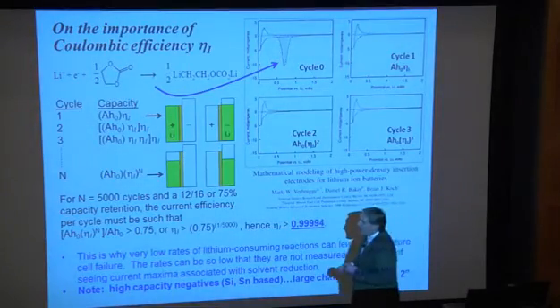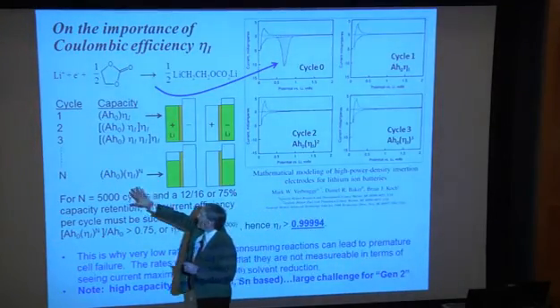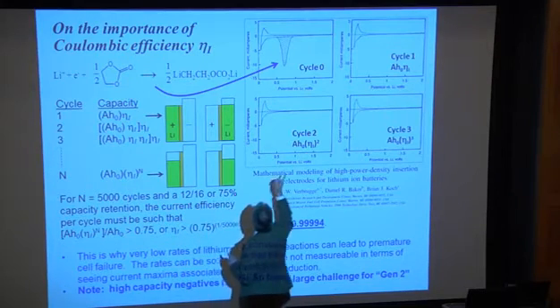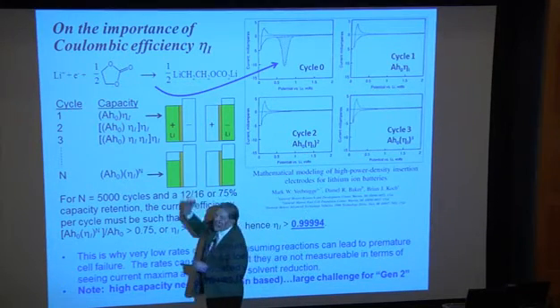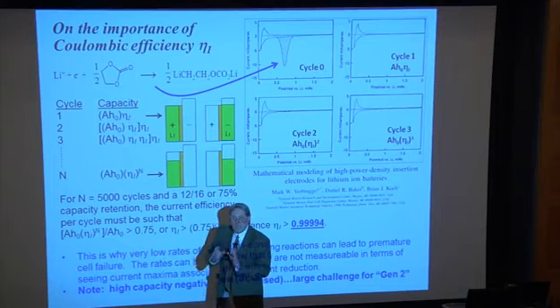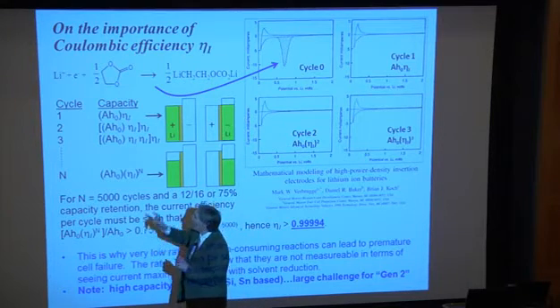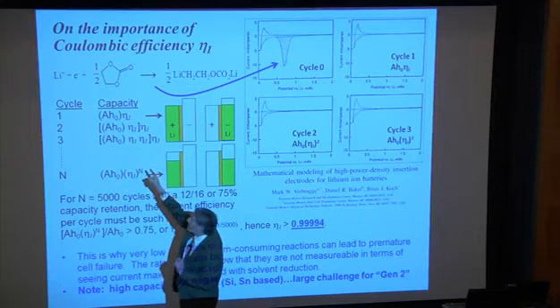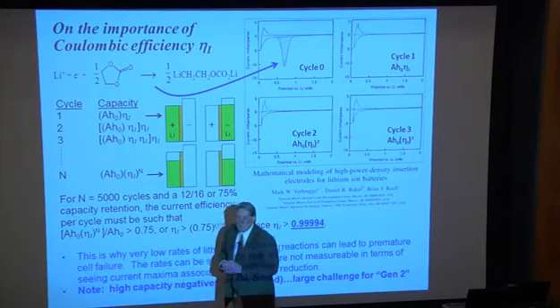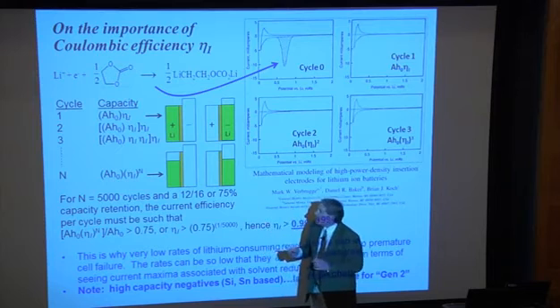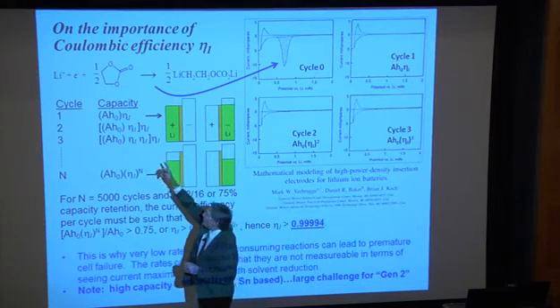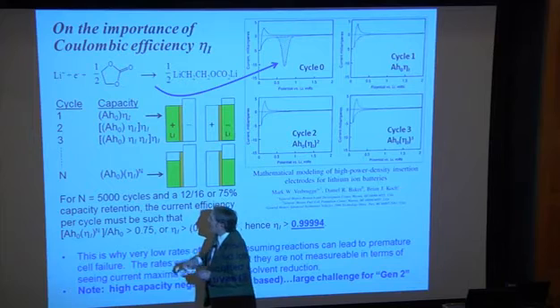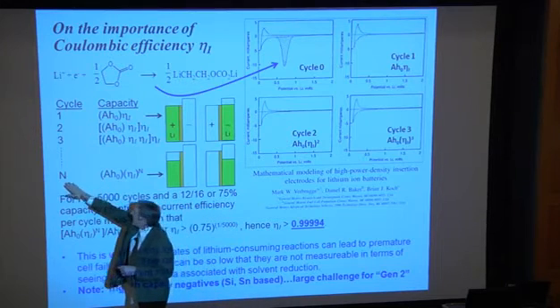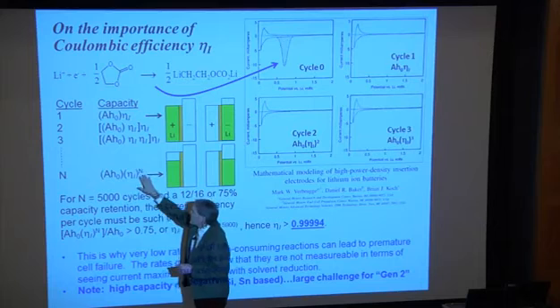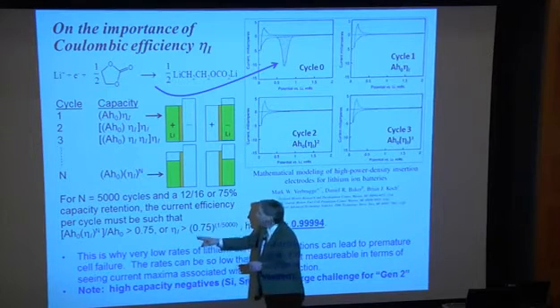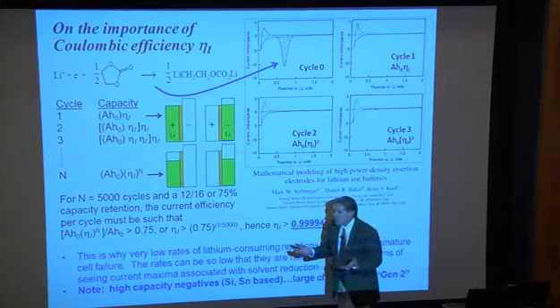And it's kind of like a compound interest problem if you figure out why this is important. Think of starting out at cycle 1 in the far right corner with amp hour naught, the nominal specified amp hours. And then after your first cycle, you're going to have a current efficiency, let's assume the current efficiency is constant, of eta sub I. Say it's 0.99 for now. And then you can walk down, and each cycle you keep on losing some capacity. In fact, you can get a very simple formula: number of cycles, amp hours naught, current efficiency, and number of cycles shown up here.